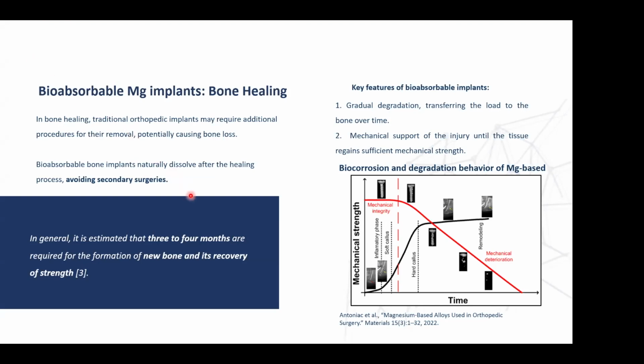So actually, one of the advantages of having bioabsorbable alloys is that, for example, we don't need to keep a permanent titanium implant after bone has healed, and this can, of course, help to avoid pain, inflammation, discomfort. Using magnesium is very interesting for this purpose. It's a very vital element, and incorporation of other elements that are similar in nature can also improve the corrosion rate. Actually, the challenge with magnesium is that it degrades fast in the human body.